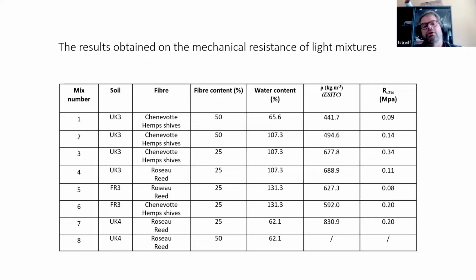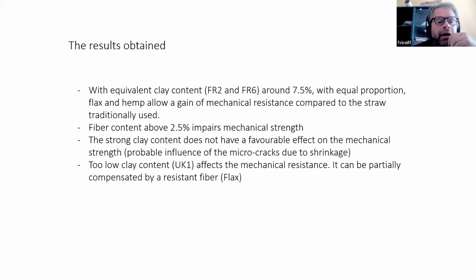Regarding the mechanical resistance, the compressive strength of the light mixture, of course, we've got some very poor results, but it's not the load-bearing part of the wall, so not really important here. So the results we obtained with this first study prove that flax and hemp allow us to gain mechanical resistance, compressive strength, compared to the straw traditionally used.